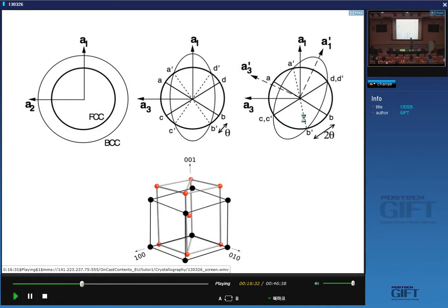So the combination of a Bain strain and a rigid body rotation can lead to coherency along one direction between austenite and ferrite, but there is no rotation which will make two lines coincident. Therefore, this is absolute proof that you cannot get a coherent interface between austenite and ferrite. It's impossible. The best you can do is get fit along one single line.